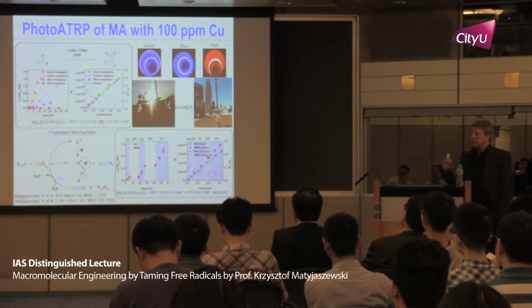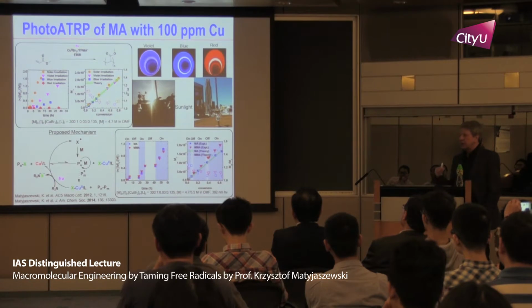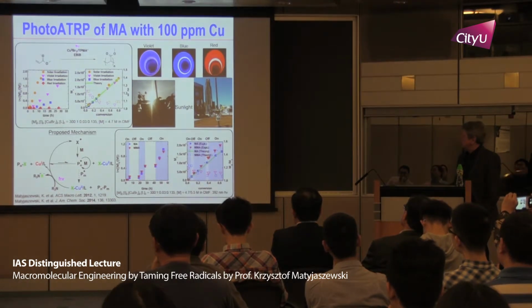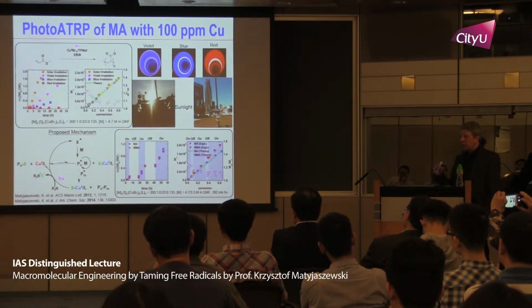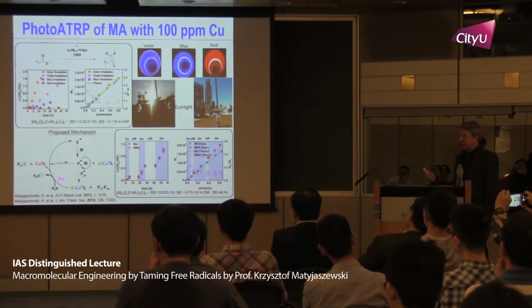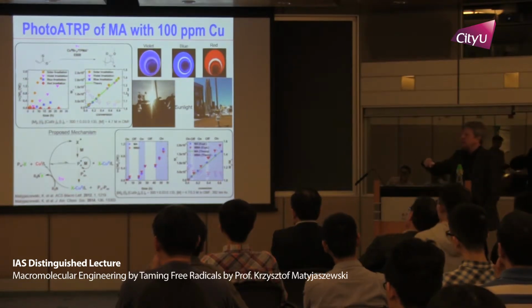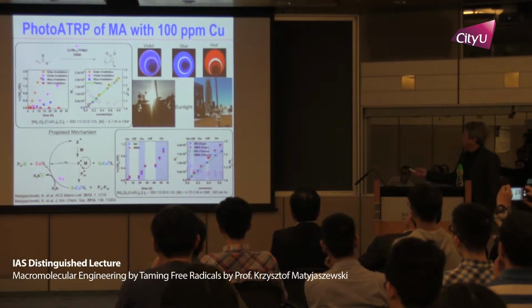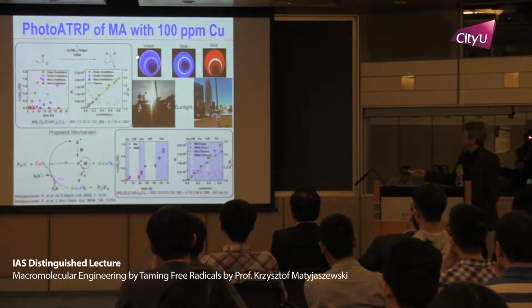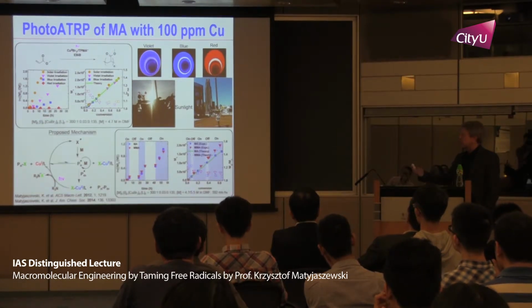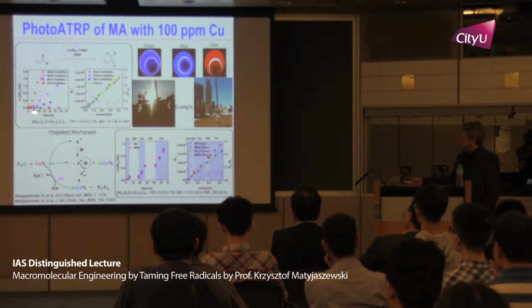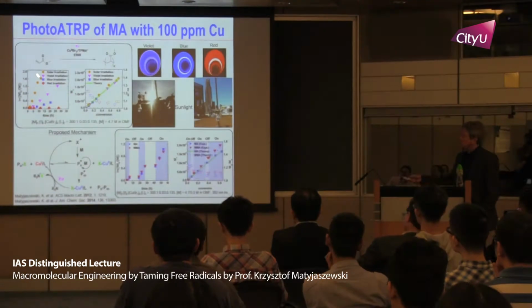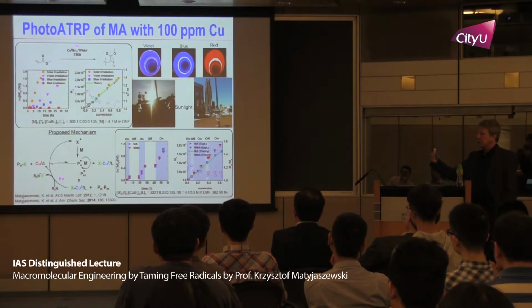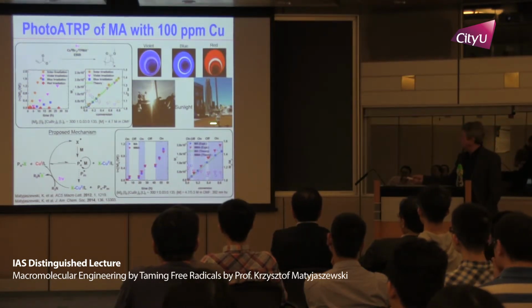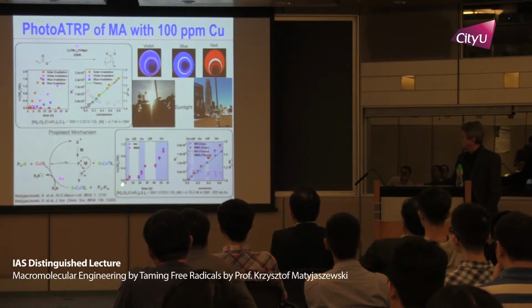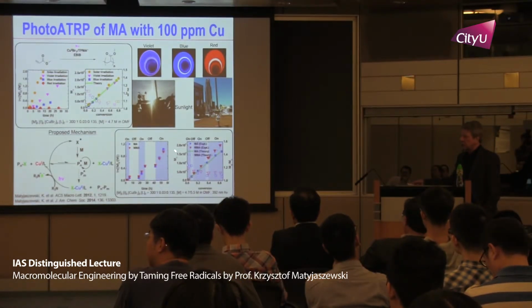So with light, you can do, in fact, two different approaches. You can activate dormant species, but also you can reduce copper 2 to copper 1 in the same way as I showed you before. So this is done in a very simple way using LEDs in a flask, and it depends whether you use red light, blue light, or violet. They interact with catalysts in a different way. Red light is inefficient. This is blue, this is violet, this is sunlight. So simply by exposing that to sunlight, this is a rooftop of Mellon Institute, you can put your flask, and during day it goes, during night it stops, goes, stops, and so on.